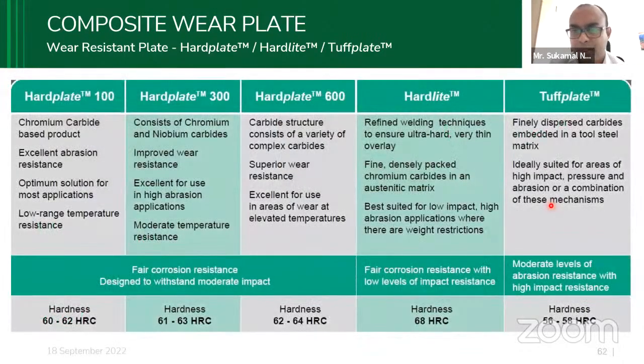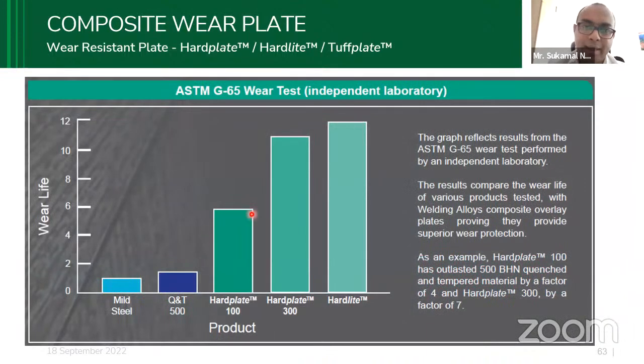Okay, so that's one. You can see here that we do testing, the ASTM G65 wear test, where these are mild steel, then quench and tempered steel, then hard plate 100, 300, and so on. You can see what I told you, that depending on the customer's requirement or the amount of life they want, we recommend the hard plates.